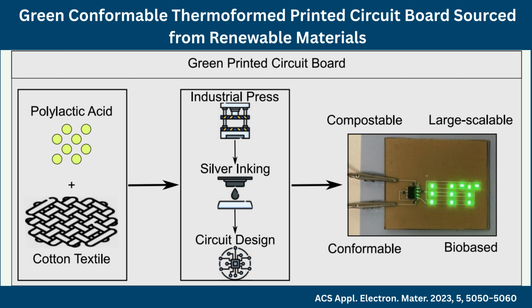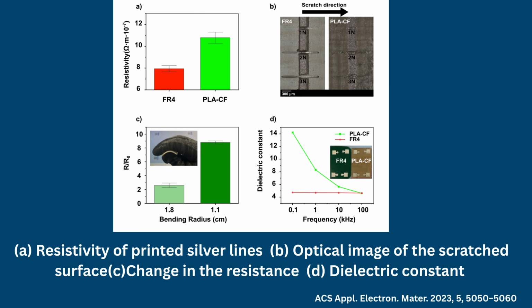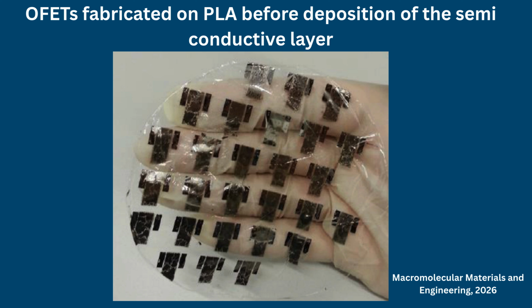PLA reinforced with flax, cotton, or cellulose fibers has demonstrated dielectric properties comparable to FR4 while enabling solvent-free manufacturing through melt processing and compression molding. Recent studies using PLA cotton laminates have shown surface roughness suitable for conductive ink printing, comparable silver track conductivity, successful micro-drilling performance, adequate dielectric constants for PCB applications, and thermoformability at temperatures near PLA's Tg, approximately 60 degrees Celsius. Unlike FR4, PLA-based substrates can be reshaped after fabrication, enabling conformable and flexible electronic devices.